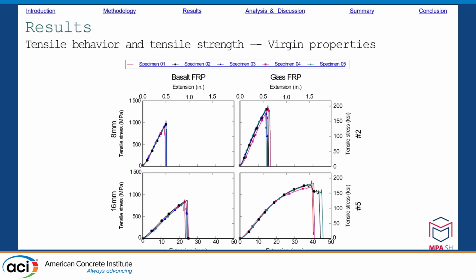Now we come to the results of the tensile and shear test, starting with the tensile test. This graph shows the result of the specimens that were not exposed to frost. The basalt fiber rods are shown on the left and the glass fiber rods on the right. The rods with a diameter of 8 mm are shown at the top and those with a diameter of 16 mm at the bottom. It is noticeable that the glass fiber rods achieve a higher tensile strength than the basalt fiber rods. In addition, all curves show a proportional increase until the maximum stress is reached, followed by a drop. The samples of the individual groups show similar values to each other.